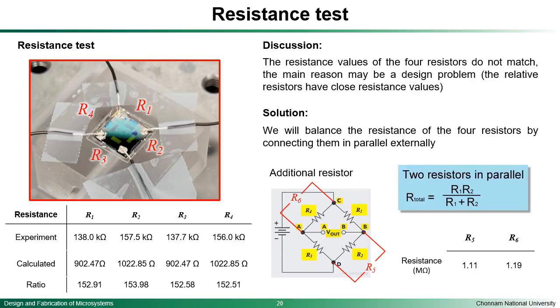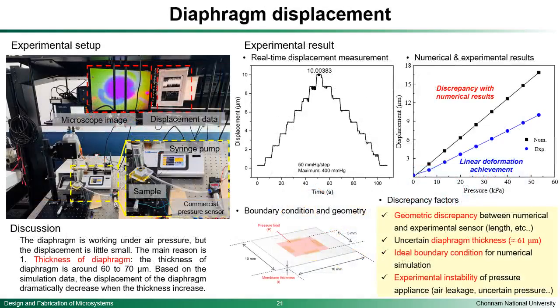So we just connect our sensor, then we test the diaphragm deformation with the laser system. Here we can see the displacement data shown by the lasers. I applied around 400 millimeters of mercury pressure, with a 50 millimeter mercury step for each pressure. When the pressure increased to 400 millimeters of mercury, the maximal displacement is around 10 microns.